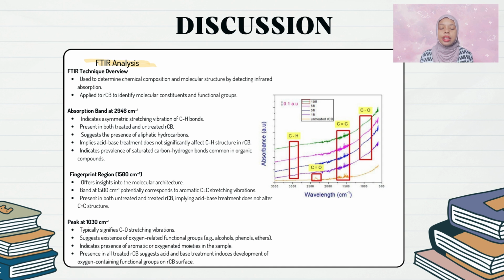Secondly, aromatic C=C vibrations. Peaks indicating the presence of aromatic C=C were also detected. Aromatic structures are common in carbon black due to the pyrolysis process, which breaks down complex polymers into simpler aromatic compounds. Thirdly, oxygen-containing functional groups. Perhaps the most significant finding was the development of oxygen-containing groups such as C-O and C=O bonds on the RCB surface after treatment. These groups were not as prominent in untreated RCB, suggesting the acid-base treatment effectively introduced these functionalities. The introduction of these oxygen-containing groups is beneficial for several reasons.